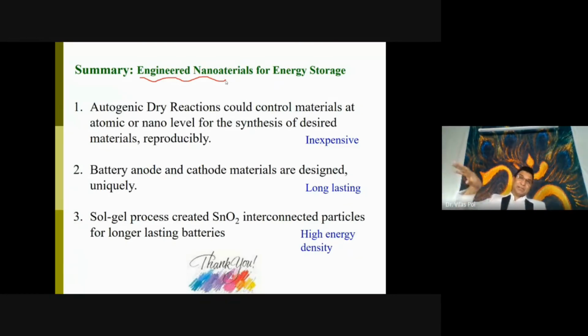And that's the reason you get longer life, because that expansion and contraction was accommodated in the electrode itself. And that is the beauty of these interconnected particles, which provide a longer life compared to the nanoparticle, which can react very effectively with the electrolyte. And if the particles are just away from each other, there is no electron hopping happening very effectively. So if the electron loss is happening, then instead of having the longer cycle life, you have a shorter one. Okay, thank you. You are welcome.